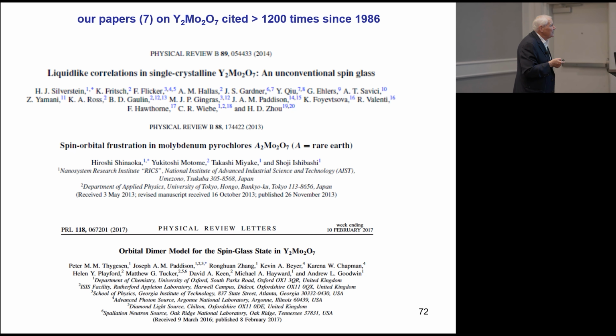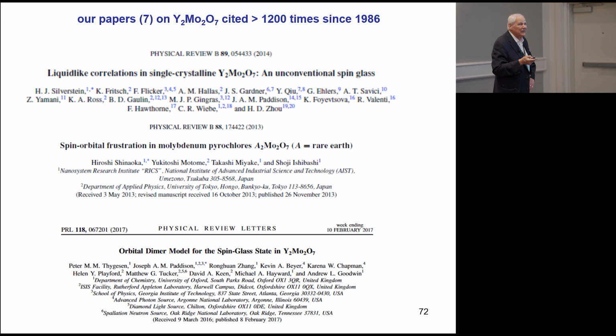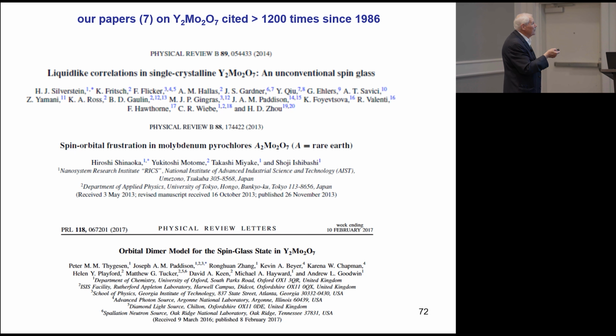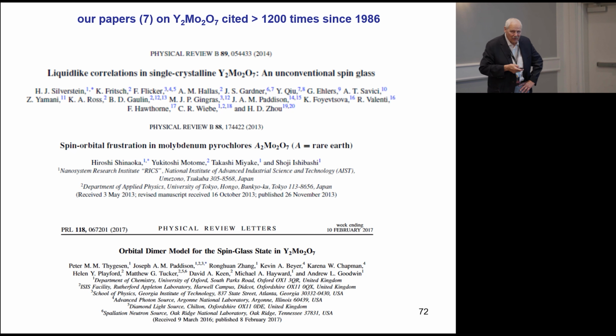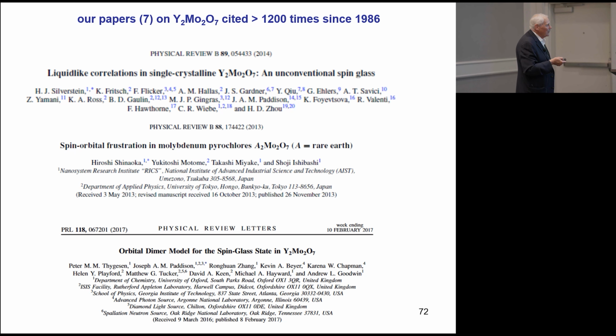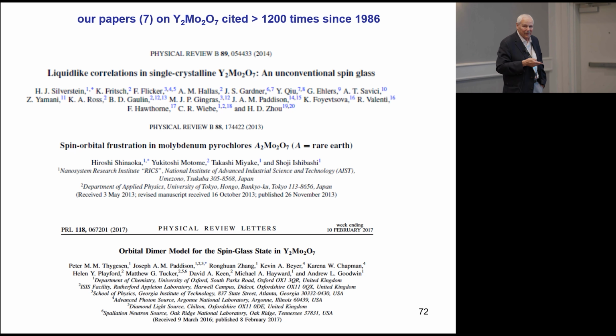Okay, since we published our original work in the late 80s and early 90s, the papers have been cited an amazing 1,200 times. So a lot of people have been interested. And there are three other approaches to working out what the disorder model is for this material. And probably the final word is here, 2017, some 30 years after the initial report of the spin-glass behavior. It's a very complex orbital dimer model of Joe Paddison using the RMC approach. And that seems to be the last word. It took 30 years to figure it out.